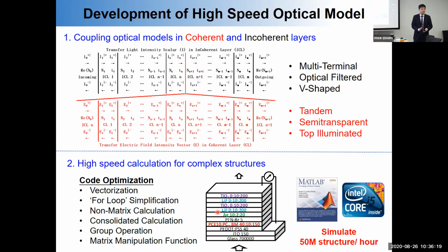Over the past couple years, I have a student who is very good at mathematics. He further improved this model. The previous model works well when the length scale of all the layers is similar. But if you have a large length scale, for example, you separate them by 1 meter, then you need to introduce another matrix, which is the incoherent layer here. So we feed all this transfer matrix model for coherent length scale into this incoherent one. Now we can expand the calculation capability.